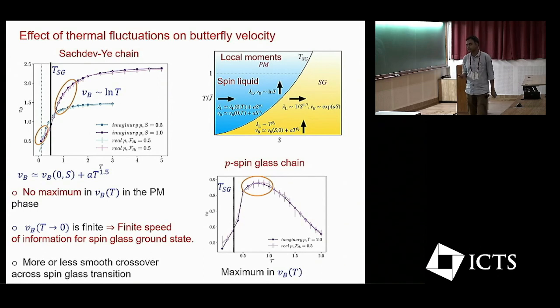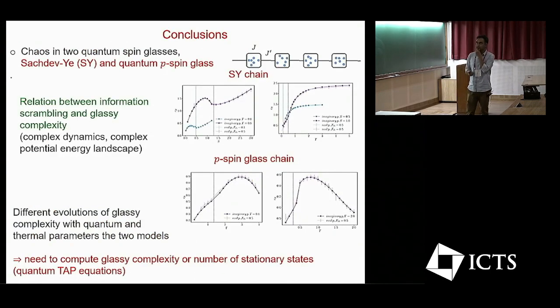So this basically suggests that you have very different evolution of complexity as a function of quantum fluctuation versus thermal fluctuation in this model. The fact that you have a maxima is probably related to this complexity, but the evolution of the complexities is very different. So the main message is that there is probably some interesting relation between information scrambling and the glassy complexity, some dynamical quantity and some quantity which you understand in terms of landscapes. It is enhancing the chaos at an intermediate temperature, and it is apparently detecting the onset of complex relaxation. So with that, I thank you for your attention.